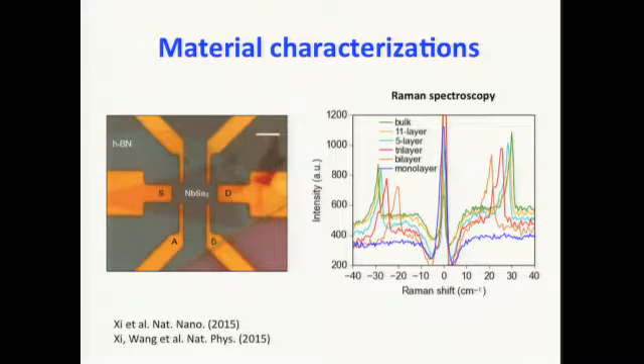And you can actually see that as we change from the bulk material down to the monolayer limit, this Raman mode, which is corresponding to the interlayer shearing vibration between the two layers, disappears in the monolayer, because there's nothing to vibrate with, so this mode disappears in the monolayer limit. So we can actually get a pretty good technique to characterize the layer number very accurately.